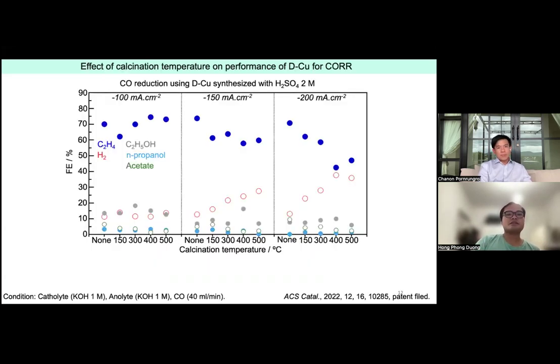Okay, the activity. Now I go to activity. We found that the dendritic copper synthesized with 2 molar sulfuric acid was the best one, and we could even reach like 70% efficiency. We surveyed three different current densities from 0.1 to 0.2 ampere per square centimeter, and we compared the sample calcined at different temperatures, and we found that the sample calcined at 400 or 500 was slightly better in terms of ethylene compared to the non-calcined sample.